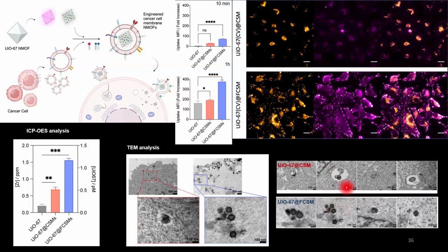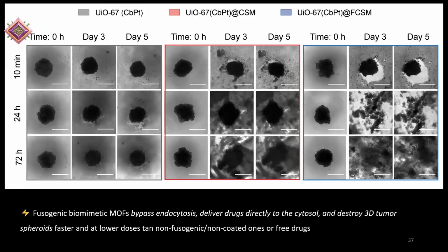You can also see this with TEM. This is when you have the coating that is not fusogenic, and you see the MOF inside vesicles. And when you have the fusosome, you don't see it in vesicles anymore. Okay? And then we loaded a drug with this particular system. With the fusogenic ones, we completely destroy the tumors, and you can follow this over time.